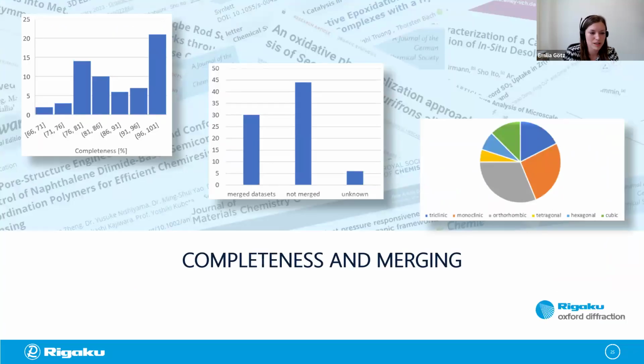Besides high resolution, it's of course beneficial to also have high completeness. And for electron diffraction, this is harder to achieve with a single crystal than with single crystal X-ray diffraction, because we can only tilt along one axis. So especially for low symmetries, we might not get 100% completeness. And we can see here that low symmetry crystal systems like triclinic and monoclinic make up almost half of the published structures. But what we can do, like I explained before, is merge data sets of different crystals together.